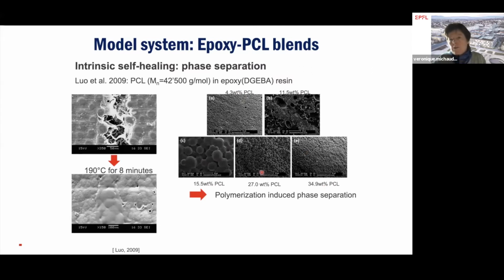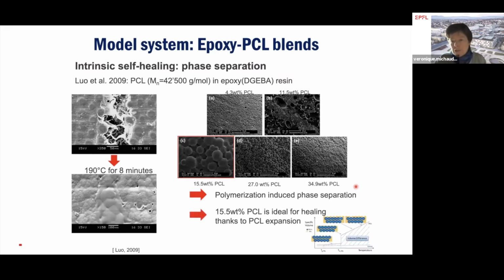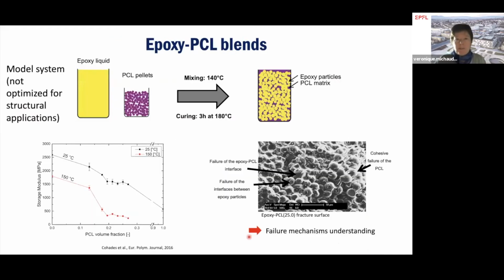And depending on the mass fraction of the PCL, you get polymerization-induced phase separation with different morphology. What he showed also is that in his case, around 15 weight percent PCL was good for the healing, thanks to the PCL expansion. And what he shows is that because of this heat expansion of the PCL after melting, you get the possibility of the PCL to bleed. And this brick and mortar morphology, as he called it, was the best one to obtain this bleeding and healing of the PCL phase.